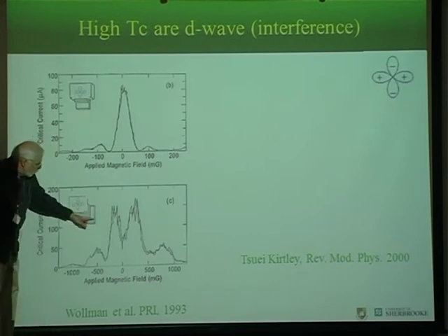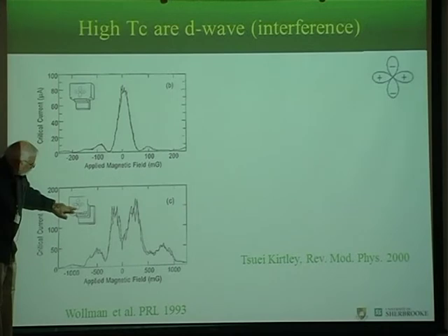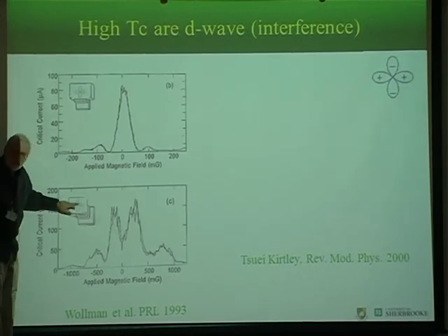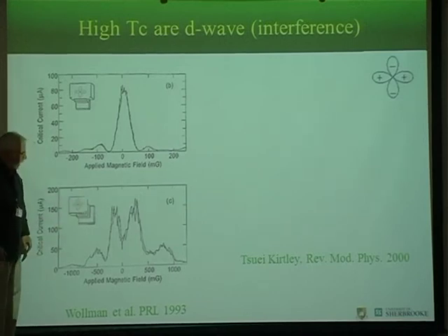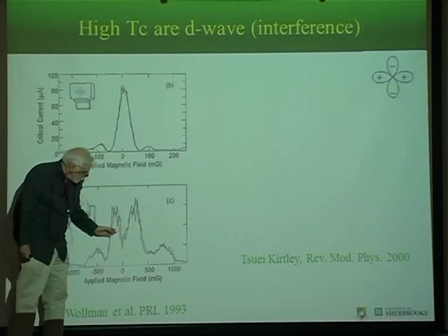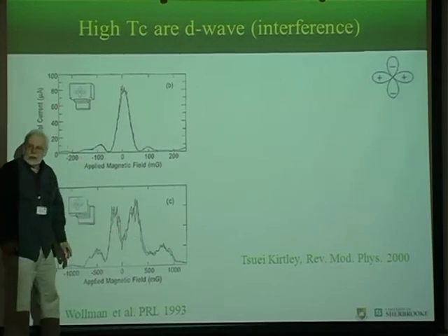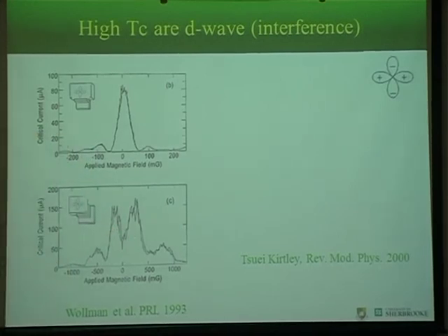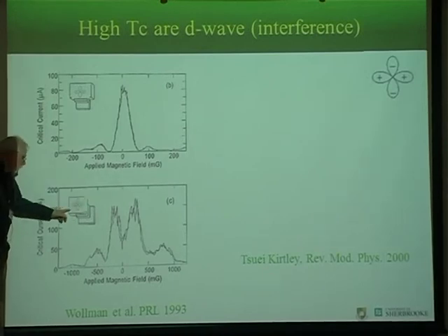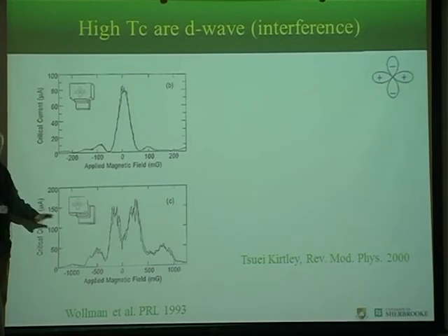Now, if you do a corner junction, now I have a D wave and I have S wave. Then there's plus, minus. So there's already a current that is circulating, even in the absence of a field. And you see that the Fraunhofer pattern is shifted here. So this is really an interference experiment that shows that there are not only nodes, but also a change in sign of the wave function.